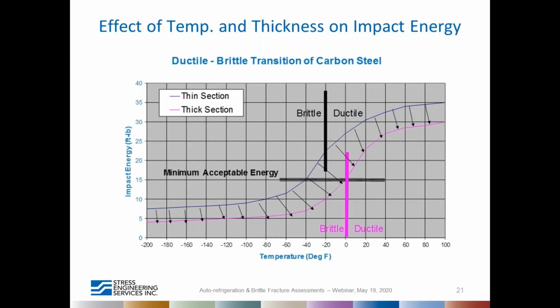We have to also look at the effect of thickness when considering the fracture toughness. For many years, the thickness effect was not considered in the codes. If you look at this graph, we know that the nil ductility temperature, or the brittle to ductile transition temperature, is somewhere here. For a common thin section carbon steel material, the brittle to ductile transition temperature is about -20 degrees Fahrenheit. Although for the same material, if the thickness is higher, the curve gets shifted to a warmer temperature. And this is one of the reasons why many of the failures were noticed in thicker sections.